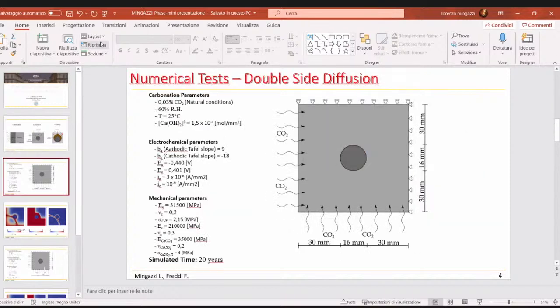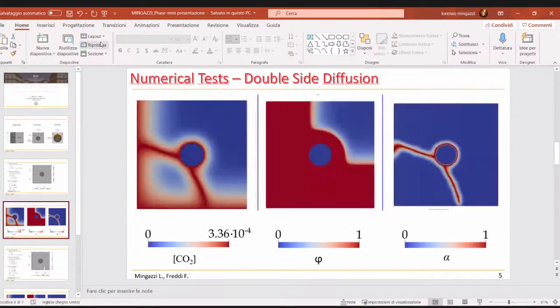So we studied two numerical tests. The first one is a double side diffusion test where carbon dioxide enters the square concrete specimen with a steel rebar placed in the center from the left and the bottom side of the specimen. And here we can see the results of the numerical simulation, where on the left side we have the carbon dioxide profile, on the central panel we have the carbonation profile, while on the right side we see the phase field.